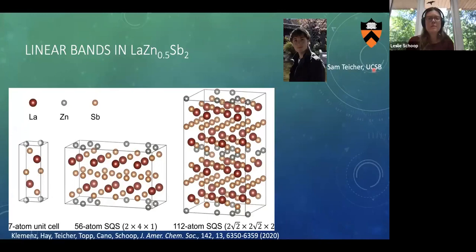So this is a unit cell of this material where you see the zinc is only half occupied. That's why it has half of a white and half of a gray sphere here. And in order to accurately model it, you have to construct a supercell. So you construct two different ones, and I will show you the band structure of only one of these supercells. Because the supercell is so large, when we expand our crystal structure, we fold our band structure, with many atoms per unit cell, and this folds it like crazy. What he did is fold it back into the original Brillouin zone, so we can compare it with materials that look like that. And so that's the band structure you get.